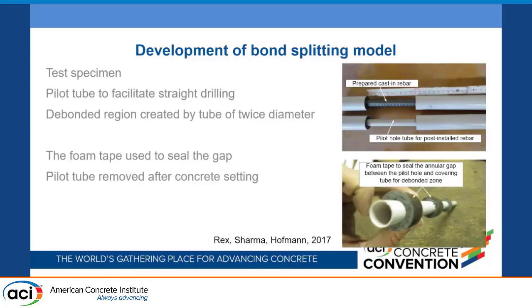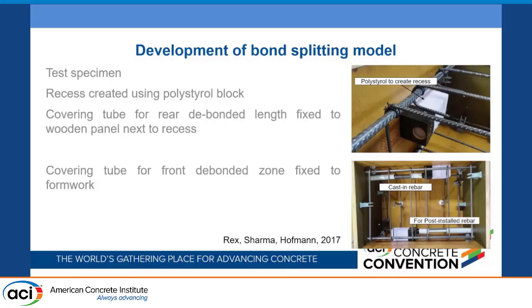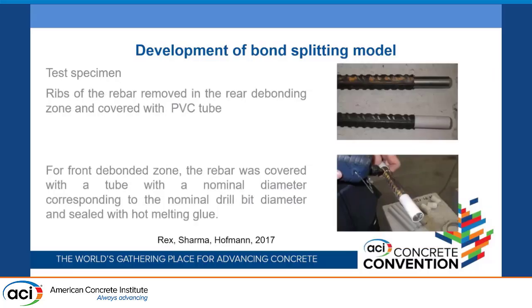Of course, it was quite some task to develop the methods such that we have clear bonded and debonded length. Justus Rex came up with very nice ideas there. He created some pilot tube so that through that we can drill it, to make sure that our drilling is good. And we had the foam tape to seal the gaps. I will not go too much into details, but we had a polystyrol block to create the recess at the rear end so that we can measure the rear end slip. And we also grinded the rebar at the end, put a tube at the back end so that we have clear bonded and debonded zone.